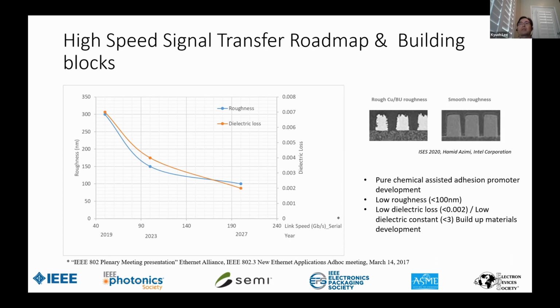But since all our direction is moving to a little bit less polarity in the buildup material, with less polarity and a very smooth copper surface, that puts a significant challenge in manufacturing because it has high resistance to dissimilar chemistry. And it also has intrinsically lower adhesion to the buildup copper.